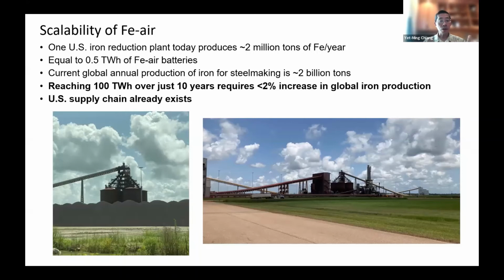These two images show the structure that you see is a vertical shaft furnace. And there's a conveyor that brings the iron ore pellets to the top. And over days, they work their way down through this vertical shaft furnace and emerge as that DRI that I showed you. On the left-hand side, those mounds in front of the shaft furnace are big piles of iron ore pellets waiting to go through the shaft furnace. The numbers you see in the text here, right? If we were to reach 100 terawatt hours, even over just 10 years, it requires less than a 2% increase in global iron production. And that's because there's such a large industry already in place for steel production. Okay? And there's a supply chain in the US, a domestic supply chain, as well as on every other continent on the planet.